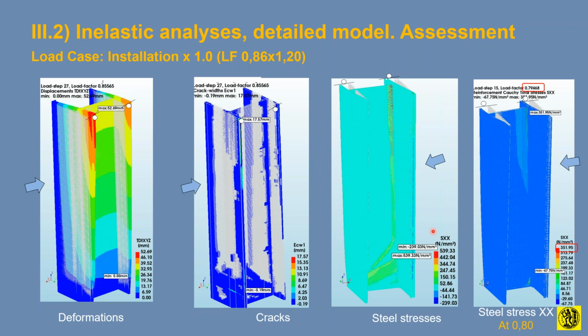Of course, we can see that here in the stresses. You can see that the stresses already here in this 45-degree, if we look at this rotated, we see that the unity of the installation, we define here already some yellow, like 250 megapascals of the steel in this area here.